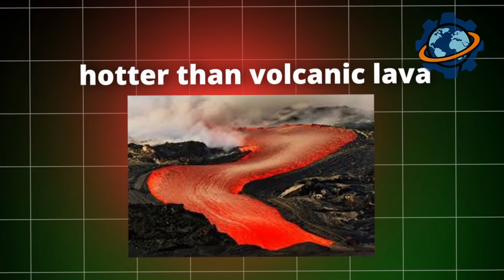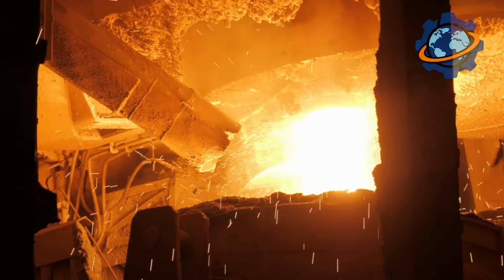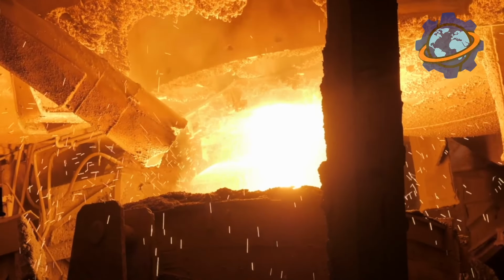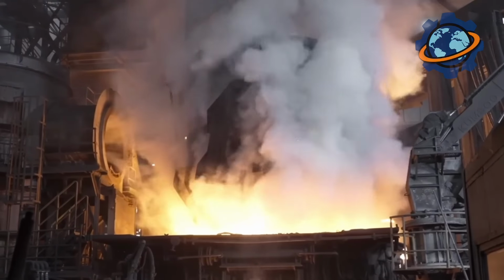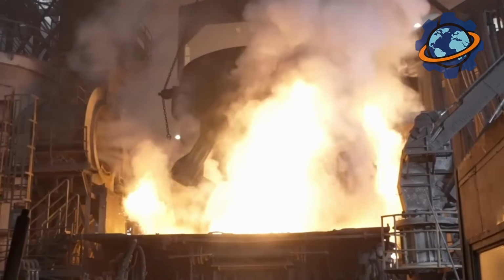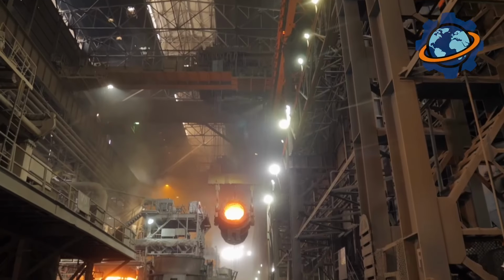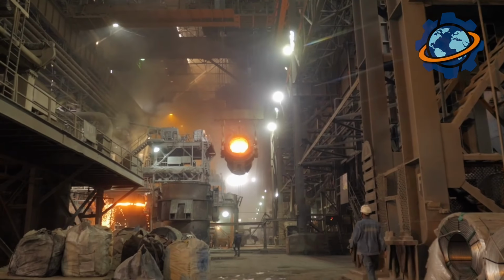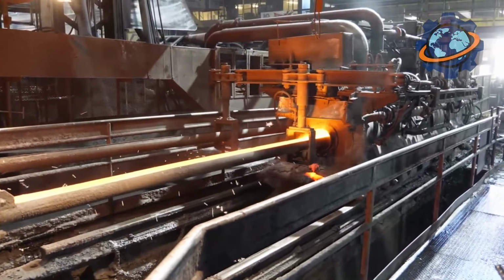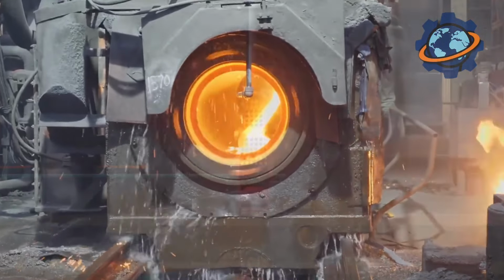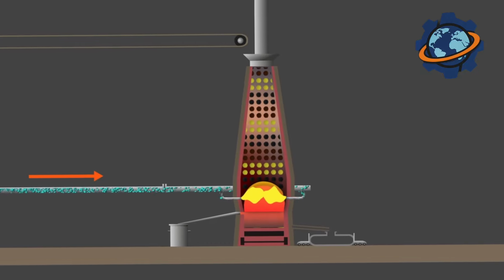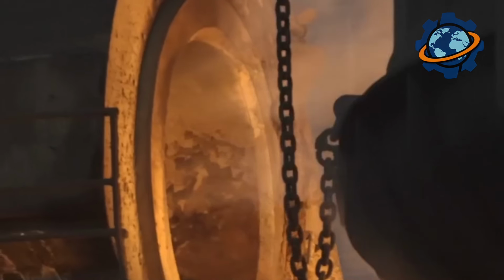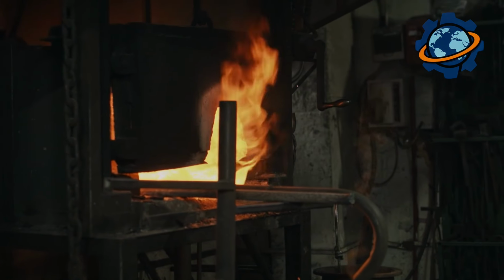Meeting the red-hot coke, the oxygen in the air instantly ignites. The temperature in this zone skyrockets to 3,600 degrees Fahrenheit, 2,000 Celsius. This creates carbon dioxide. But as it rises higher and passes through new layers of coke, it turns into another gas, carbon monoxide. And this gas is the real oxygen thief. As this searing hot stream of gas rises up the furnace shaft, it envelops the chunks of ore and begins to greedily rip the oxygen from them, leaving behind reduced, spongy iron.